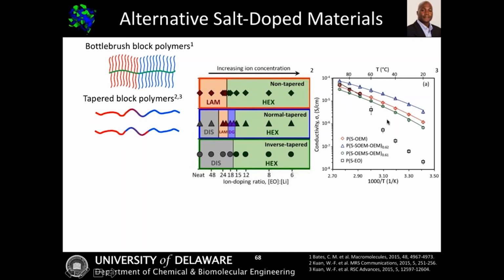So in this particular case, what I'm showing is the example of that normal taper. So the blue colors here actually correspond to each other. And basically what you can see is that by putting in that tapering, we're actually able to get higher conductivities than we do in both the neat material, which is shown in red, as well as than just the typical PS-PEO material, which is shown as the black symbols.